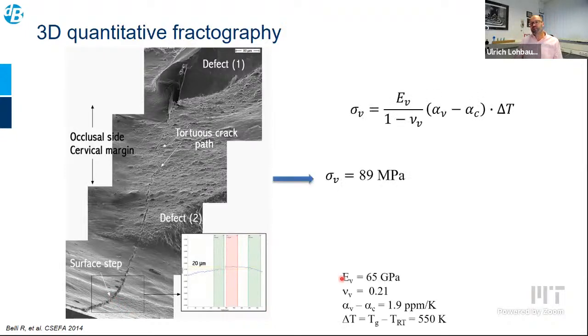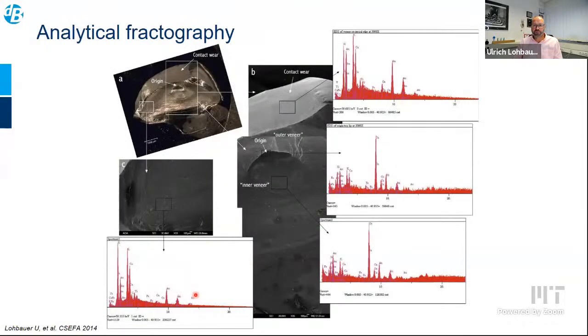This is an indication of residual thermal stress that might emanate from different coefficients of thermal expansion from the veneering porcelain to the core material that creates residual stress, and those residual stresses are creating the defect in the end.